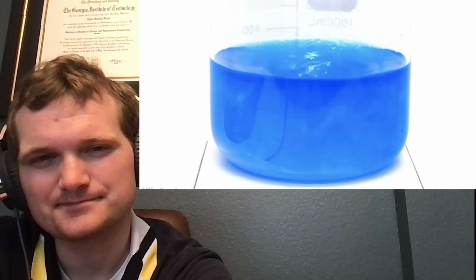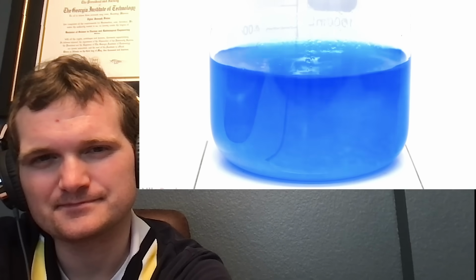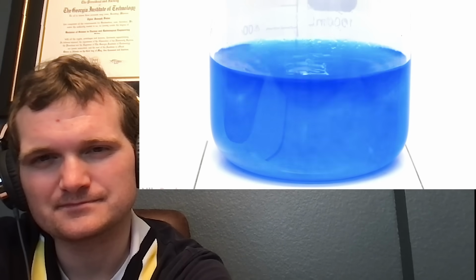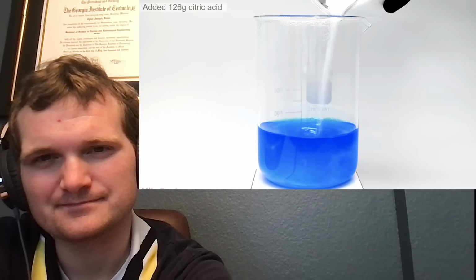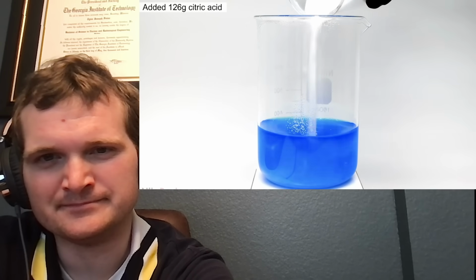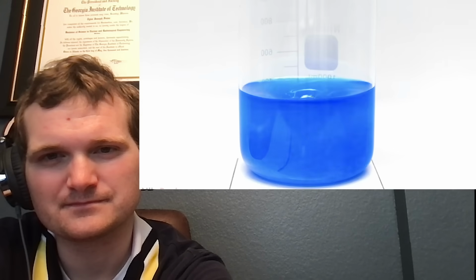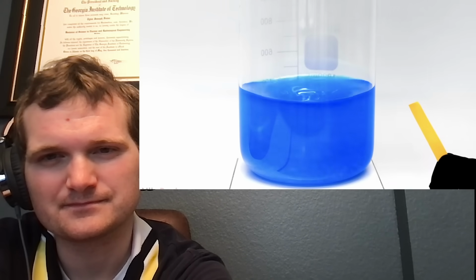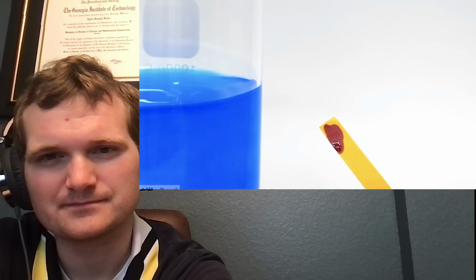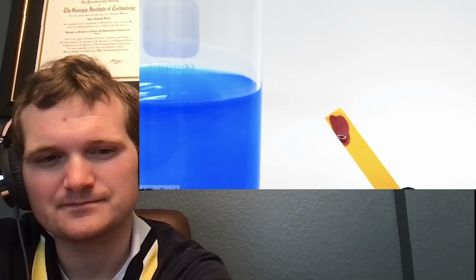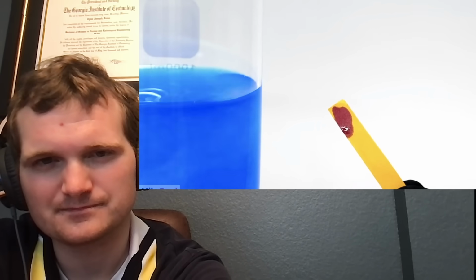I then waited until it looked like all the yttrium had disappeared. However, exactly when that happened was a bit hard to tell because there was still so much barium floating around. When it eventually seemed okay, I added the final ingredient, which was a bunch of citric acid. I let this stir for about 20 minutes, and then I checked the pH. The red color told me that it was quite acidic, and it was probably around a 1 or 2.